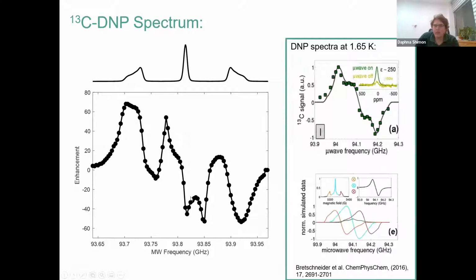So in the literature, if you look for similar types of diamond powders, there's this really nice paper by Christian Bretschneider and Lucio Frydman, and they did DNP of carbon in diamond powders at low temperatures, 1.65 Kelvin, but at the same field and similar powders. They had a DNP spectrum here at the top, which doesn't show as many features as the one that we see, but it looks pretty similar.